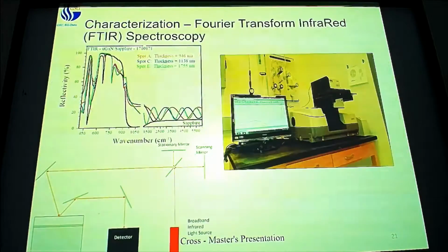Okay, and then the heart of my work, which I've enjoyed doing, is the Fourier transform infrared spectroscopy. We take a sample, put it into the FTIR spectrometer, which takes the light, bounces it here, and has a scanning mirror. So we can vary the intensity of the wavelength that is actually reaching the sample, and we measure that signal coming out. And that variation is a function of wavelengths. So we need to take the Fourier transform of that in order to get our spectrum coming out of that. And again, this provides us the information about the thickness. You recognize those thickness fringes, which are the same as before, although shifted up in wavelength.